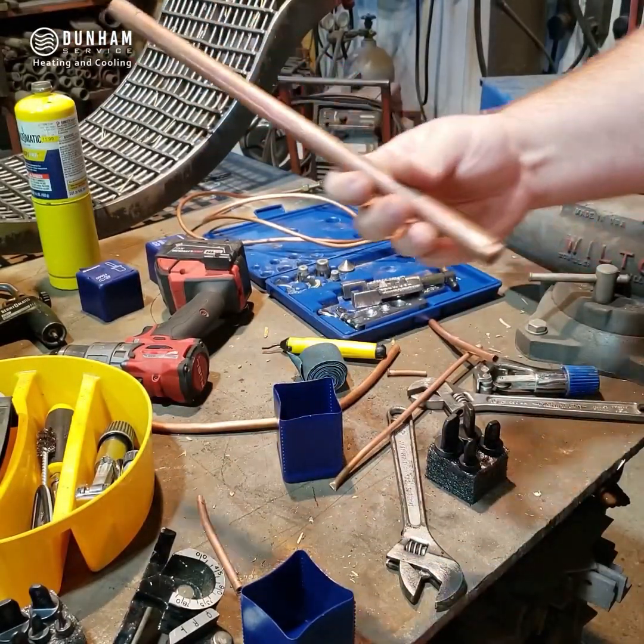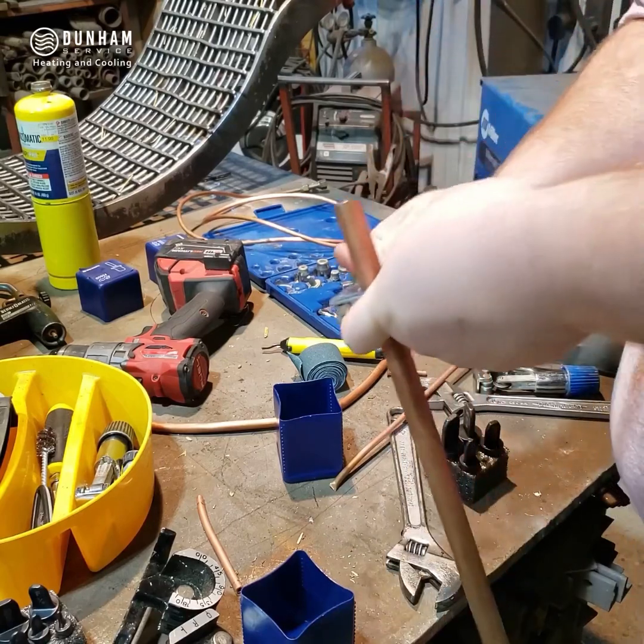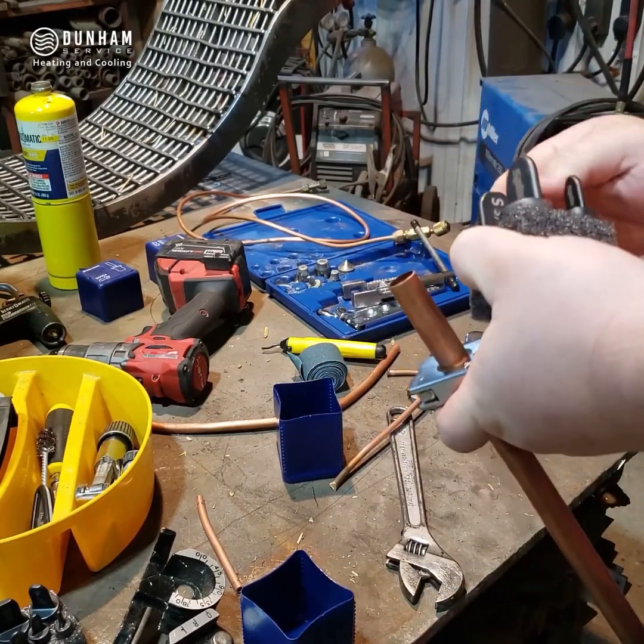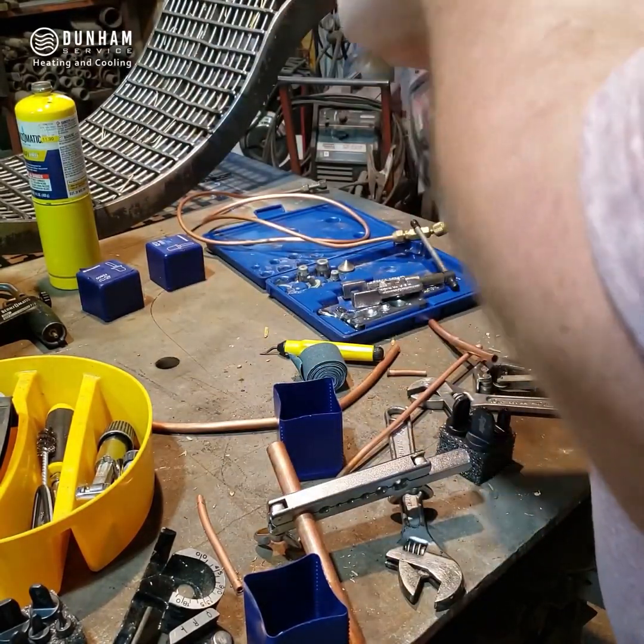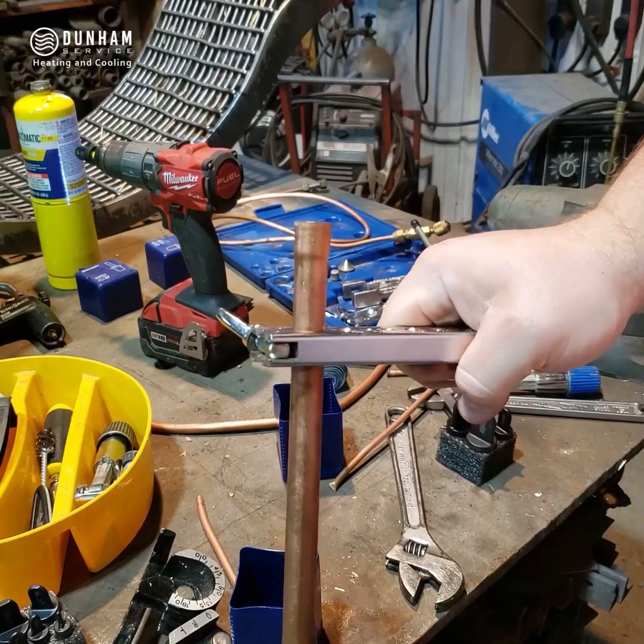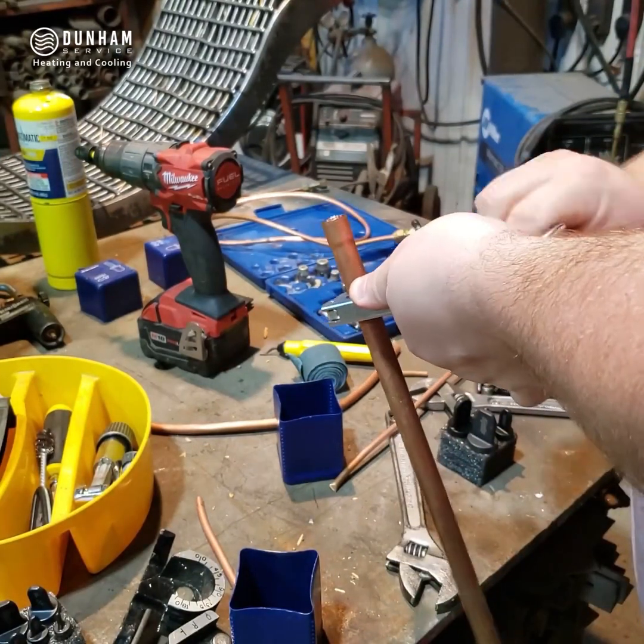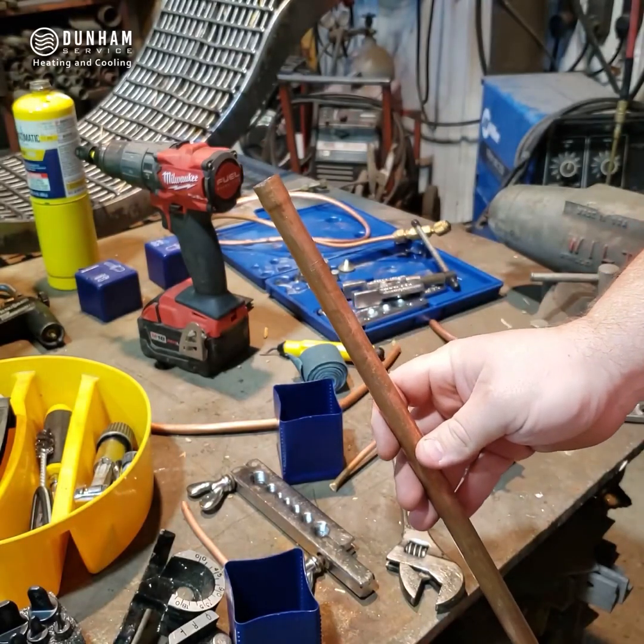Here I have a piece of hard, rigid copper, and I'm going to go ahead and tighten it into the vise. This is going to be five-eighths, so I'll change my bit. The benefit here is that the heat anneals the copper and allows you to do it to hard copper without potentially splitting it. Then another piece of this would fit right inside.